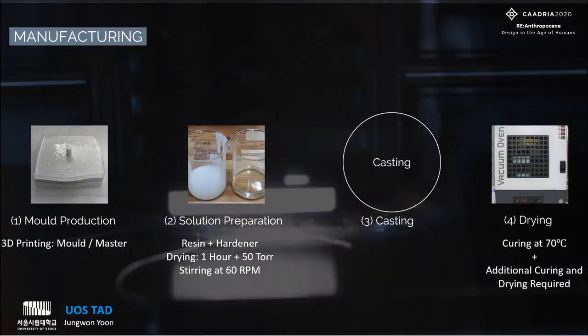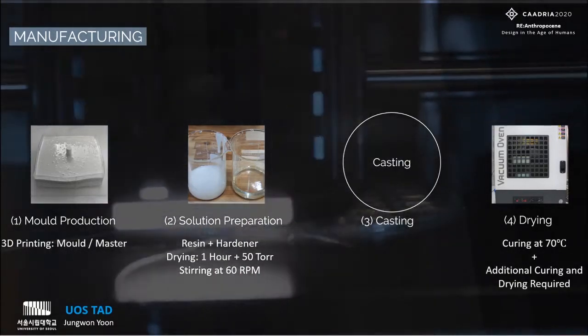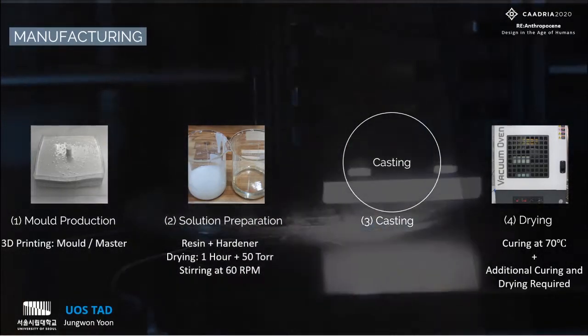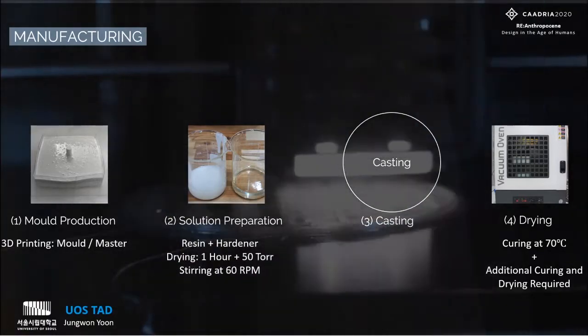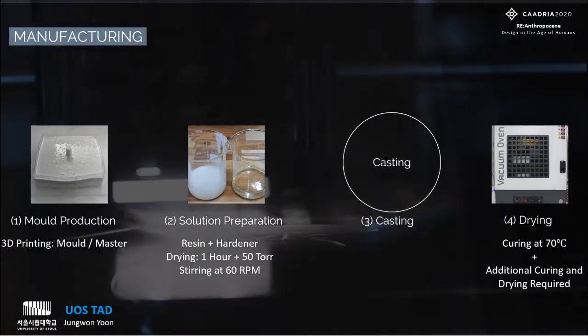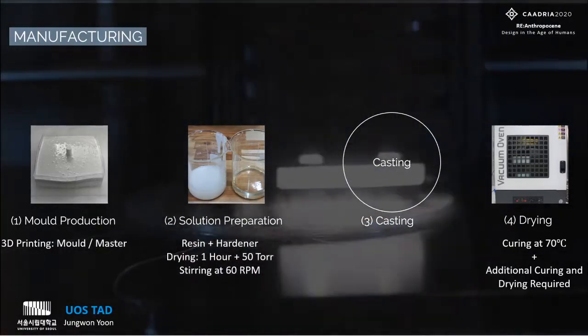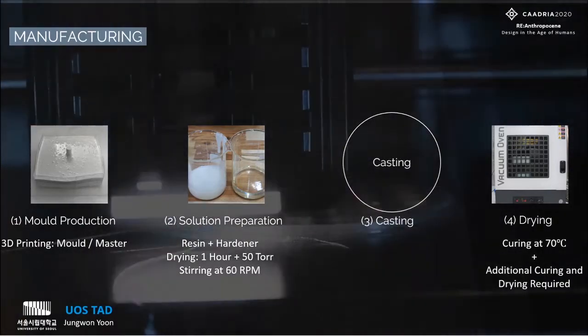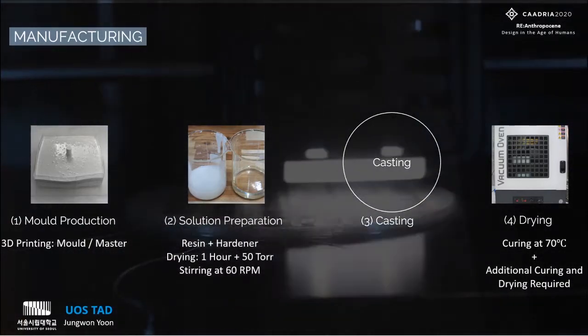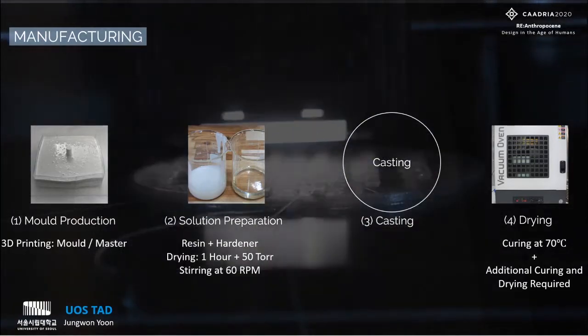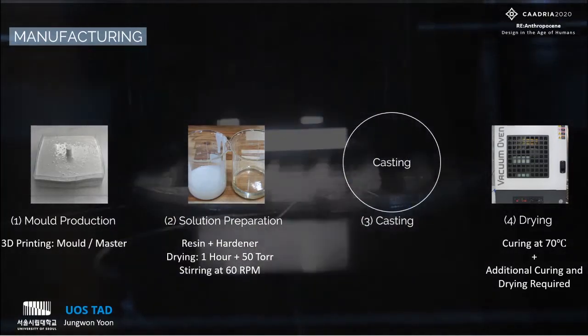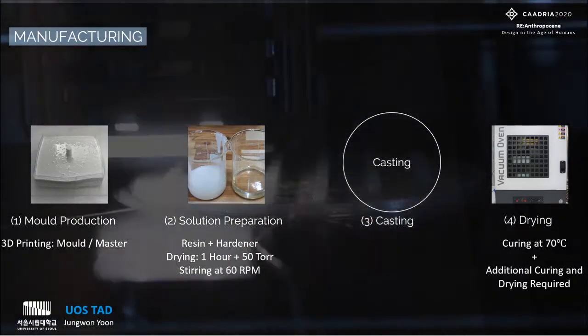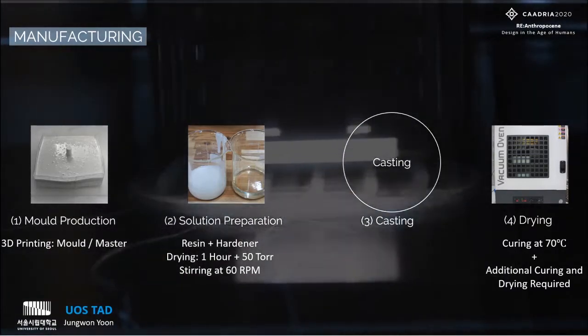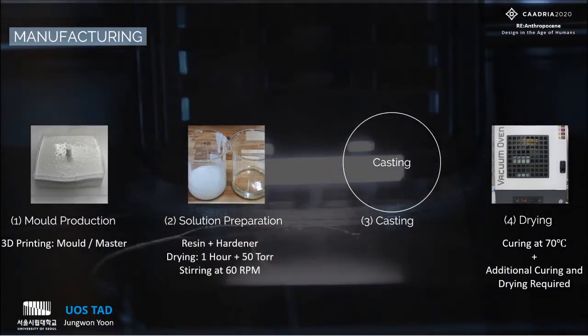In mold production, 3D printing was also applied to make ABS molds as well as to make ABS masters for silicon molds. In solution preparation, the resin and hardener should be dried for 1 hour at less than 50 torr before being mixed by stirring for 30 seconds at 60 RPM and being poured into the mold. From now on, I will share the design and manufacturing processes and results per type.